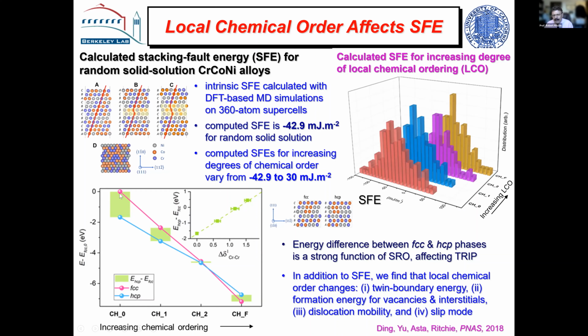We also found that the stability of the face-centered cubic versus the hexagonal phase varied with increasing ordering. If you had a random solution, then the lowest energy structure was the hexagonal phase, which is consistent with this negative stacking fault energy. But as you increase the degree of order, it stabilizes the face-centered cubic phase. Now that's important because you don't want too much hexagonal phase. We also found that it affected the twin boundary energy. It affects the formation energy for vacancies and interstitials. And as I'll show you, we didn't do this, but Evan Ma subsequently did some MD calculations where it was found to affect the dislocation mobility, and it affects the slip mode. So this seems to be a pretty profound thing.